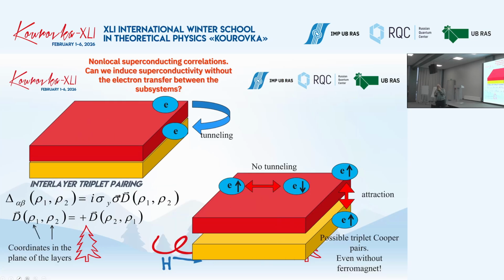And what is interesting is that in this case, this interlayer pairing becomes, well, a sort of different from standard Cooper pairs. Look, speaking of standard Cooper pairs, we usually assume that they are singlet. Why? Well, if we have just point attraction, this means that to arrange a triplet pair, we should in some sense have two spins in the same position. And this is bad because of the Pauli exclusion principle. This is why, on a qualitative level, standard Cooper pairs are usually singlet with opposite spins, because it's not forbidden by the Pauli principle.